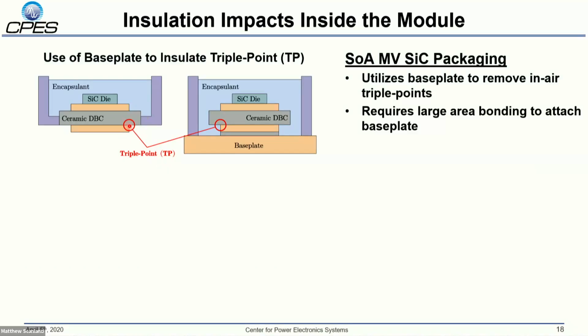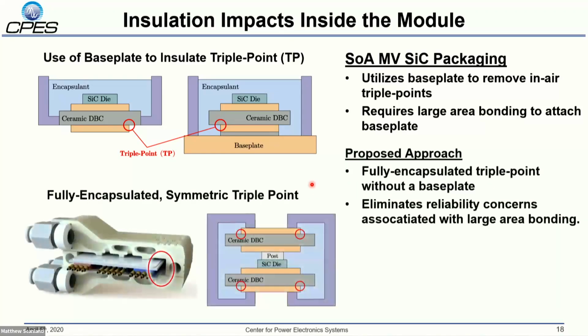Usually the way this is mitigated in conventional medium voltage packaging is with the addition of a base plate. So by adding a base plate to the module, you can now fully encapsulate the entire substrate and encapsulate both the top and bottom side triple points to get a little extra performance out of the substrate. What I'm proposing is a little bit different. I'm proposing that we can fully encapsulate the substrate, but do it without a base plate. So the benefit here is we get rid of some of the reliability concerns associated with the large area bonding, but we maintain this fully encapsulated substrate.